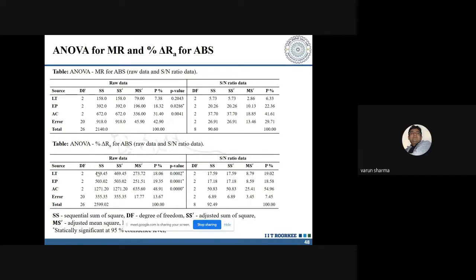Fine. Now, there was a report or work done recently that said all the parameters are significant. Whether you work with ABS or PLA, irrespective, extrusion pressure is significant, layer thickness is significant, abrasive concentration is significant, which is not the case for the additively manufactured part, at least. The reason is that this is a polymer-based media, and we have changed the media itself. With the same media, because it had a higher viscosity, it was giving a better shear thinning phenomenon. Fine. Now the parameters also changed their role.